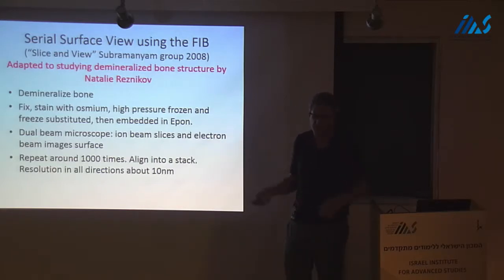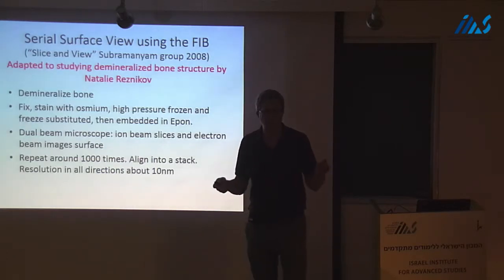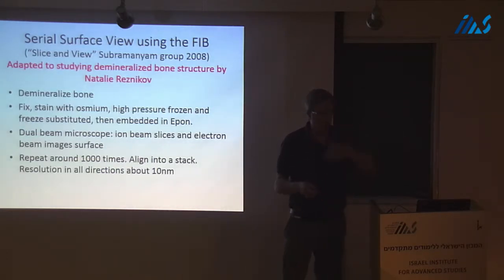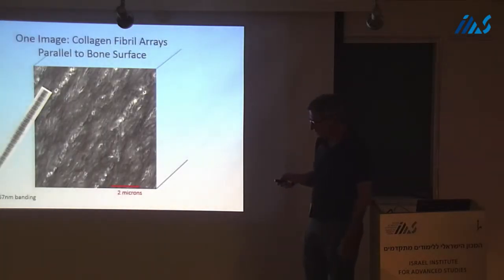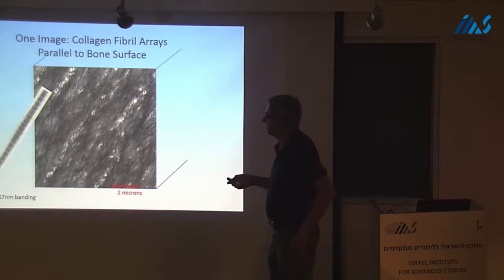Freeze substituted, and then embedded in a plastic to maintain the structure. If you just dry or distort the structure, you're lost. Then you use the dual beam microscope to make the slices, and you repeat this 1,000 times, and then you align it into a stack. The resolution is the same in all directions, which makes interpretation much easier.